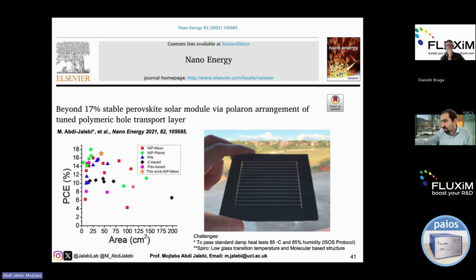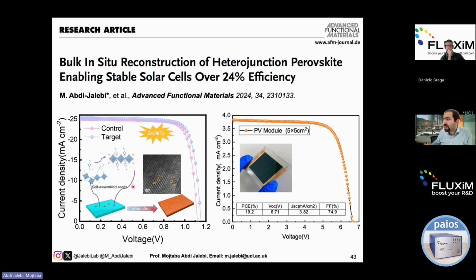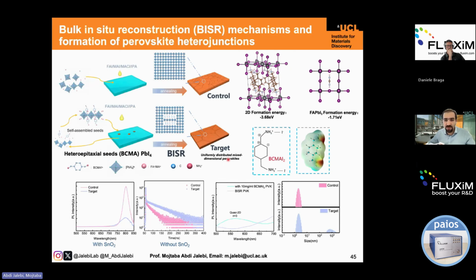So that was the summary of this work, where we were optimizing which molecular weight of PTAA works best. And finally, in this work, we also play with the dimensionality of the perovskite to make the device more stable. One of the key themes in the field of perovskite is how we can mix the 2D phase of the perovskite with 3D, because 2D is much more stable compared to the 3D phase, but on the other hand, the 3D phase shows higher performance. So one strategy is to mix the 2D and 3D, either in a multilayer or in the bulk. But the problem is that normally it's challenging when you have an extra layer of 2D, or you have some mismatch in the crystallinity.